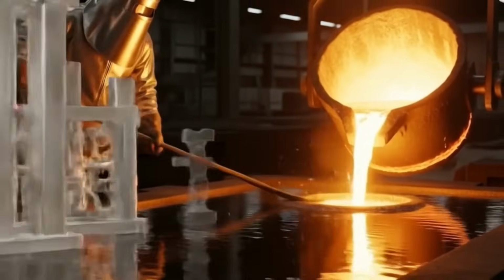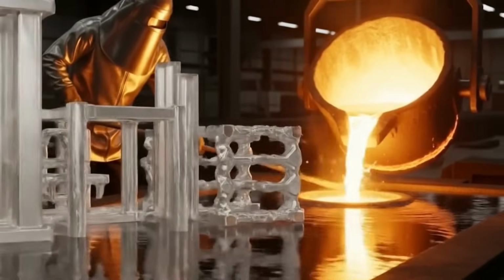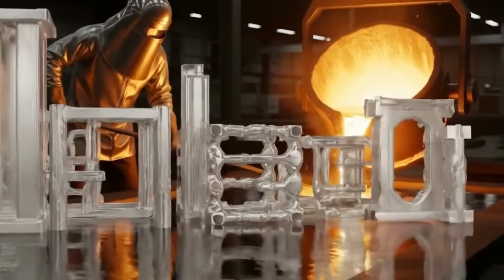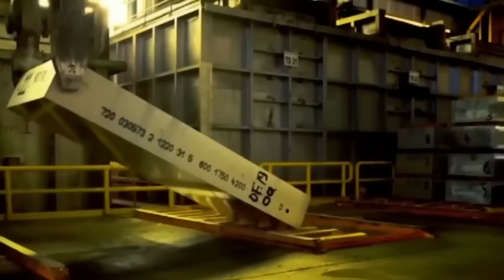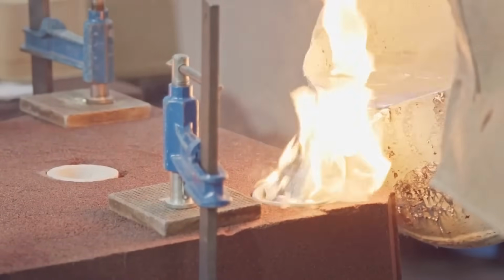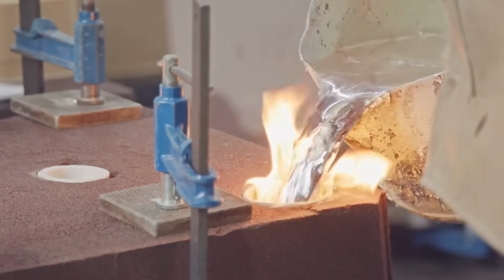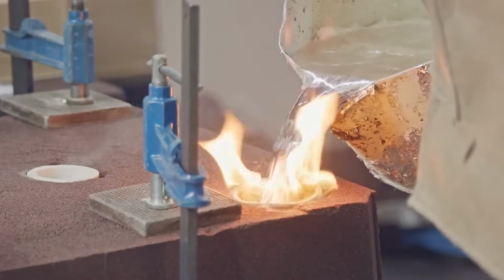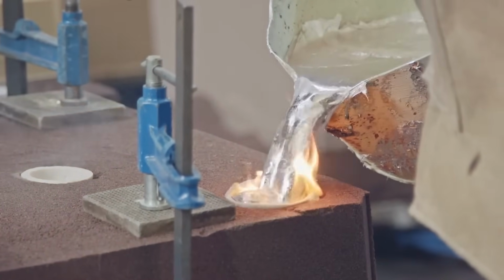The process begins with alumina being added to massive electrolytic cells, or pots, each lined with carbon. On its own, alumina's melting point is over 2,000 degrees Celsius, which would be impossible to handle on an industrial scale. To make things practical, engineers dissolve the alumina in molten cryolite. Cryolite is a rare mineral, but here it acts as a solvent, bringing the melting point down to about 950 degrees Celsius. That's still hot enough to melt rock, but now it's manageable with the right equipment.